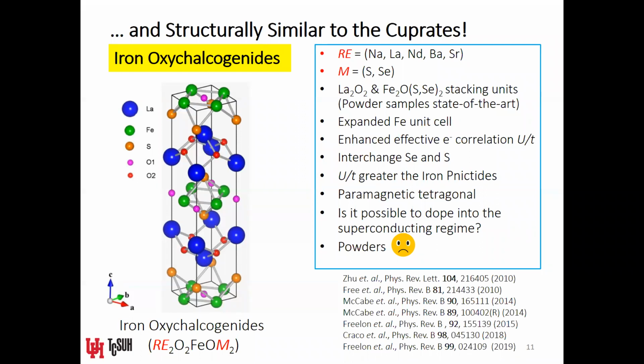So it turns out after a lot of trying that these materials can't really be driven into the superconducting phase, okay? But it turns out that they can only really be well made in powder form, okay? But because they have a close similarity to the pnictides, mainly that their level of electron correlation can be tweaked beyond that of the pnictides, they're interesting to study in terms of learning about materials that are close to the iron superconductors in the phase diagram, okay?